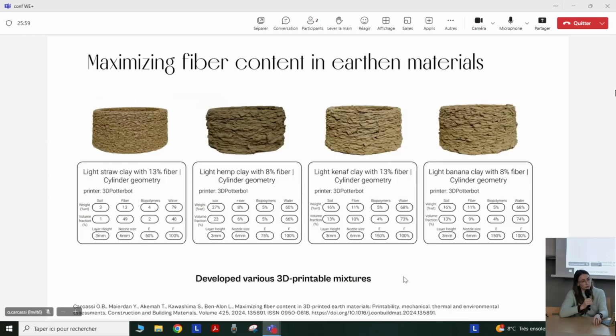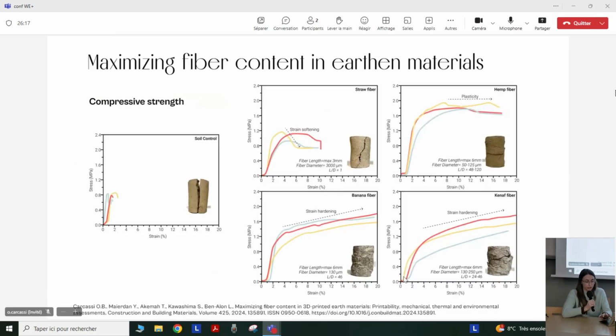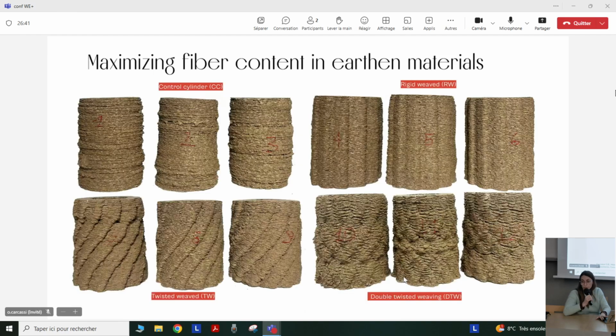So according to the location where you are, you have specific clay minerals in your soil, and you have specific fibers that you have in abundance. So really translating this research finding according to your location was one of the most important achievements that we made in our research. And then we tested the materials in order to really understand their properties. And if you can see here, this is the soil control, so no biopolymer and no fibers. You can see that the rupture is very brittle, so it stops immediately. But with the addition of fibers, you can really see that the plasticity is happening a lot. So there's really something happening with the inclusion of these elements.